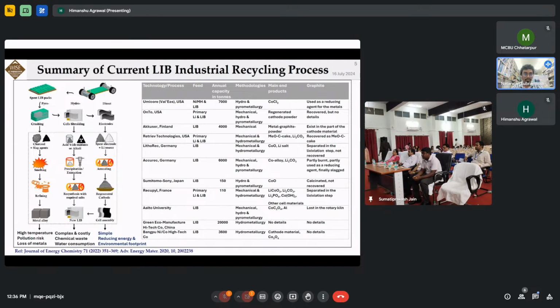and it will be converted as an alloy. But for the hydrometallurgy method, you can see there are inorganic acids like hydrochloric acid or sulfuric acid used with some other oxidizing agent like hydrogen peroxide to leach out the metals, and finally it will be precipitated out and extracted for battery production. Regarding the direct recycling methodology, the electrodes will be recovered from the spent battery and mixed with the lithium source, and it will be annealed to regenerate the cathode material, and eventually it will be assembled for battery production.